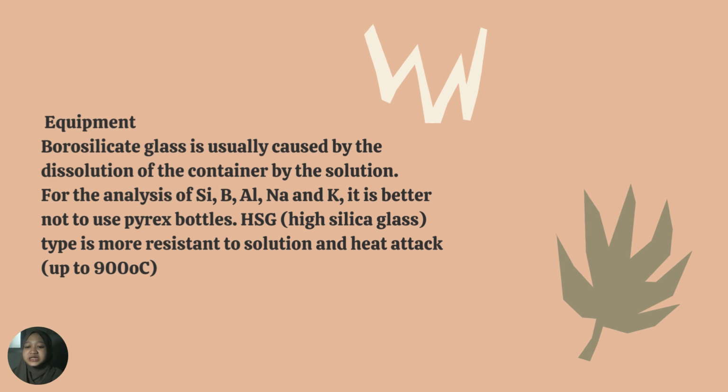For the analysis of Si, B, aluminum, natrium, and kalium, it is better not to use Pyrex bottles. HSG or high silica glass type is more resistant to solution and heat attack up to 900 degrees Celsius.